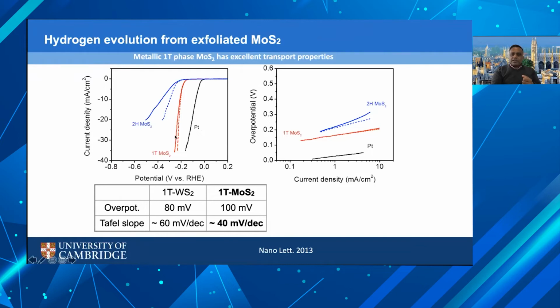So if we compare the 1T, that is the metallic phase of MoS2, we can see that there is some overpotential that is required for the reaction to proceed, and then the reaction proceeds fairly efficiently. We can compare the reaction kinetics by plotting the overpotential as a function of current density to obtain these linear curves from which we can extract what's called the Tafel slope. Okay, so the lower the Tafel slope, the better it is. For platinum, it's on the order of 30 to 35 millivolt per decade. And for 1T MoS2, one can see that you have a Tafel slope around 40 millivolt per decade. And an overpotential, that is the additional potential that's required above the thermodynamic potential to split water, is around 100 millivolts. These values are, of course, not as good as platinum, but they're still very good because 100 millivolts you can easily get from the open circuit voltage of a photovoltaic, and 40 millivolts suggests that the kinetics are reasonably good and not sluggish.